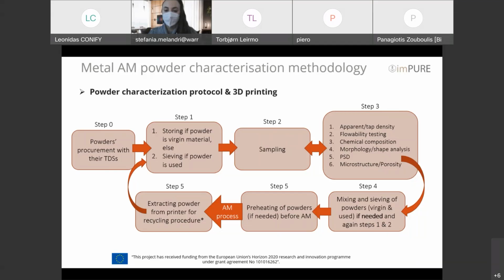And of course, we cross-section powders in order to observe their microstructure and whether they have any internal gas pores from the atomization process, for example. The next step is to mix and sieve the powders, virgin and used, if necessary, and then repeat steps 1 and 2. Of course, for the additive manufacturing process, depending on the powder, we might even preheat it before the additive manufacturing process. And then the printing takes place, and we extract our powder from the printer for the recycle procedure to be repeated. So next slide, please.